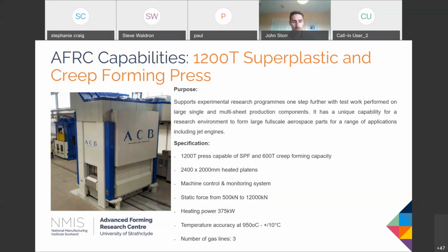As shown, compared to the 200 ton press where we had a platen size of around 720 millimeters, we've got quite a significantly larger heated platen area in this press of 2.4 by 2 meters. And that allows us then to work directly with our customers on full-scale manufacturing components, which allows them to carry out research on our presses without having to take their presses offline, which is a huge benefit for them. They don't lose production time, and then we can apply directly to prove out the process that we are wanting to investigate on that full-scale equipment, which is really essential for what we want to prove. Let's move to the next slide, please.